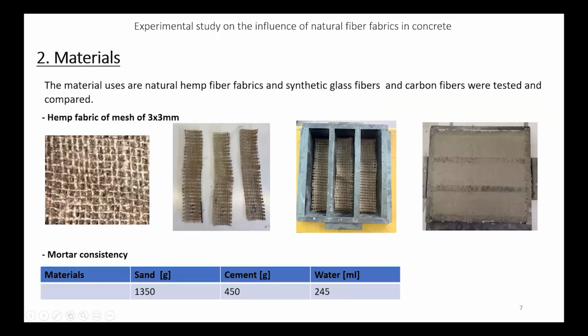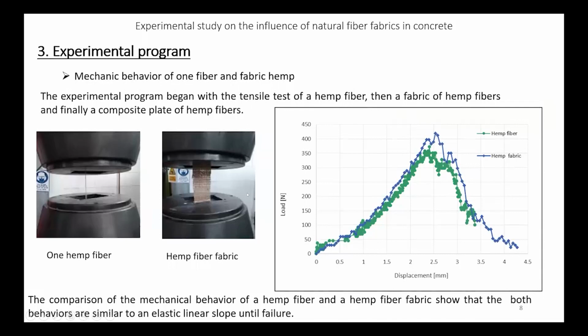So we use hemp fiber fabrics with a mesh of 3 millimeters. You can see it in the picture here. We prepare it and put it directly in some cases of our research, and after we put the mortar, which consists of sand, cement, and water. You can see the proportions here. And before this, we also studied the mechanical properties of hemp in a tensile test.